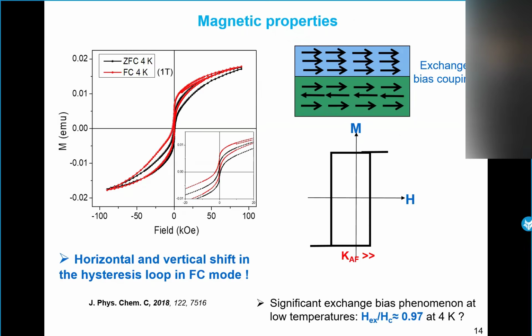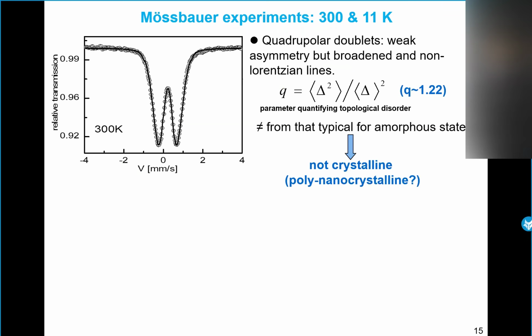For that we performed Mössbauer spectrometry. At room temperature, we obtain doublets, slightly asymmetrical. It's not easily seen, but it is slightly asymmetrical and characterized by broadened lines, non-Lorentzian lines, so typical for an amorphous structure. To reproduce this spectrum, we need to correlate the distribution of the isomer shift with the distribution of quadrupolar splitting. The fit is very good, and we obtain the parameter Q, a parameter quantifying the topological disorder in the case of amorphous materials. The obtained value is totally different from the value of the amorphous state. So the structure is not amorphous, but it is also not crystalline.